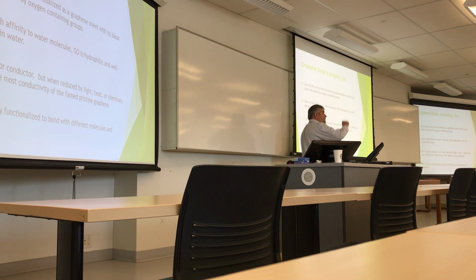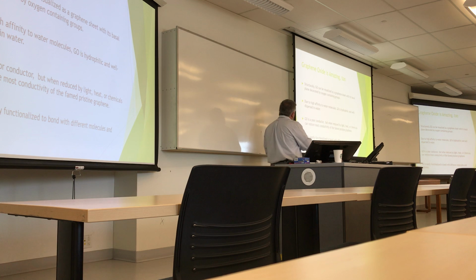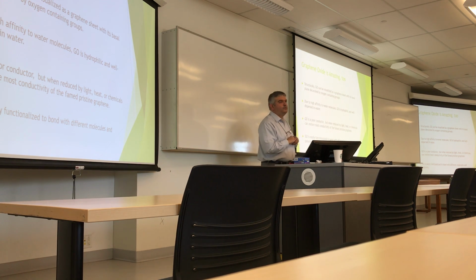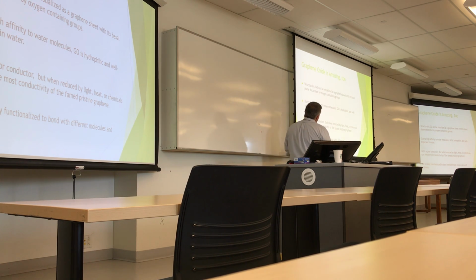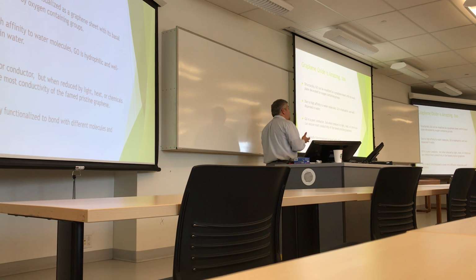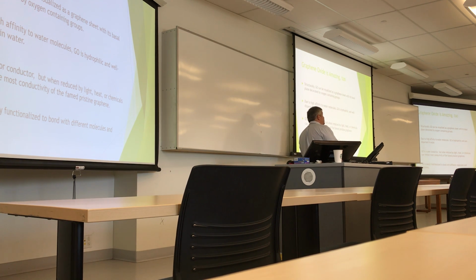Okay? And from there, we started doing some of our research that I will tell you about, but before going there, let's look at graphene-oxide. Graphene-oxide is basically the same as graphene. It has just some oxygen groups on it, different groups, and it's hydrophilic, at least that's what we thought at the beginning. Because it doesn't have that much carbon and has all the oxygen groups, it's not that conductive anymore. And because of the bonding, it's easy to functionalize.